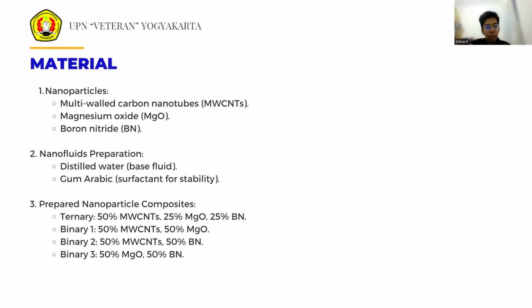So, there's the material. We have nanoparticles: multi-wall carbon nanotubes, magnesium oxide, boron nitride. Second, we have nanofluid preparation: distilled water and gum arabic. And the third, we have ternary 50%, binary 1, 2, and 3.